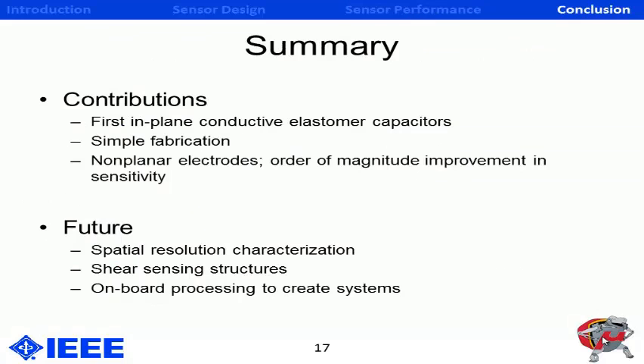So in summary, the contributions of this work are the first in-plane conductive elastomeric capacitors. It utilized a very simple fabrication process. In this process, we were able to create non-planar electrodes, which showed an order of magnitude improvement in sensitivity. And in the future, we'd like to do a spatial resolution characterization of the structure I showed you earlier. Also incorporate shear sensing structures using a multi-mask process so that we can create a mold with multiple depths. And lastly, in the long term, fabricate onboard CMOS integrated with our sensor.